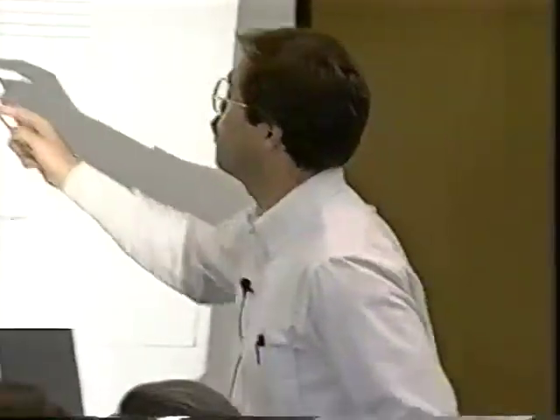With that scale being cracked in that fashion, it allows the later pickling process to attack the scale from more than one direction. It allows the pickling acid to get down into the scale cracks and down underneath. So it increases the pickleability, if you will. For those of you who purchase hot roll skin pass, hot roll pickle skin pass, we can perform that skin pass with that reduction mill there, so that we don't necessarily have to take it to a standalone unit. There's some economies there that we'll take advantage of.